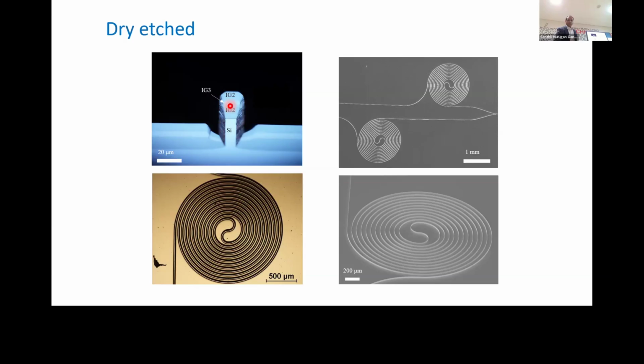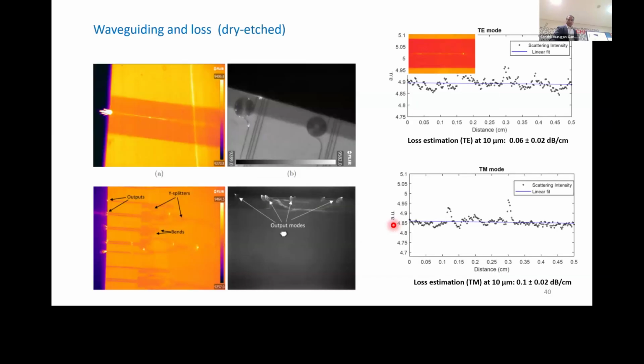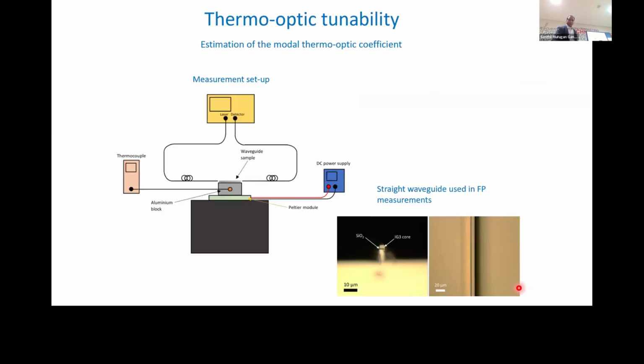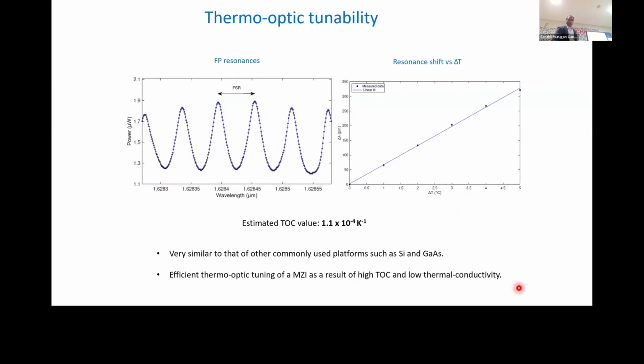Therefore, we formed a waveguide cladded between low refractive index layers, and we formed the same Mach-Zehnder interferometer on chip, and these are the spirals to increase the optical path length. Therefore, the resolution of the spectrometer is better. What you are seeing is the loss of the waveguide. We achieved 0.1 dB per centimeter, which is the lowest achieved so far in chalcogenide. And we have calculated the thermo-optic coefficient using the setup I showed in the last slide.